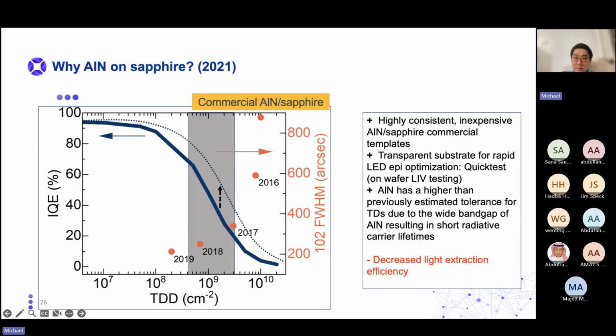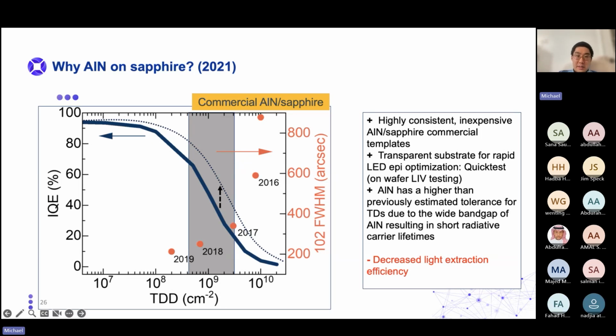Another benefit is that aluminum nitride actually has a higher IQE than previously estimated. This dark blue line was what people were talking about in terms of the theoretical absolute maximum in IQE, with the amount of defects in the material. IQE is internal quantum efficiency. But what we discovered is that aluminum nitride and high aluminum AlGaN is more tolerant to these defects than we previously thought, due to the wide band gap of aluminum nitride and AlGaN, which results in very short radiative carrier lifetimes. So the carriers do not have enough time to move to find the defect before they recombine. This definitely gives a wider range of defect densities that are usable for UV LED devices.